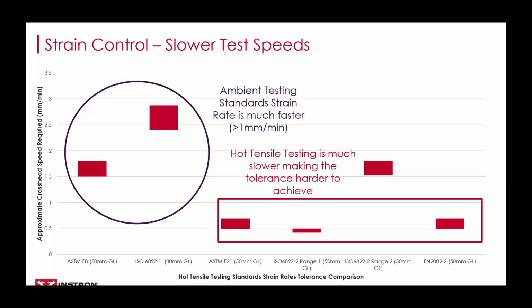You'll notice there's one set of speeds outside of the typical range of hot tensile testing. That belongs to ISO 6892-2 method B testing, which when you compare to the range on the left, there's a narrower range of conforming speeds than the ambient test due to the smaller gauge length of high temp specimens. And again, with method B, that's typically something that we see more often with research or academic settings.